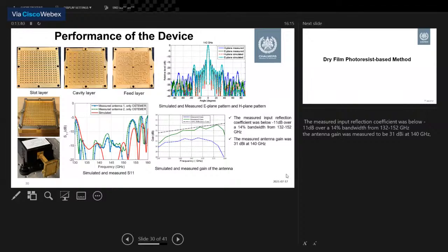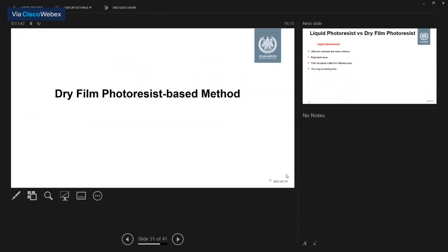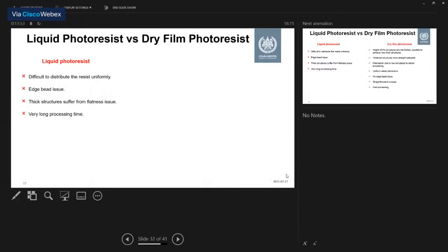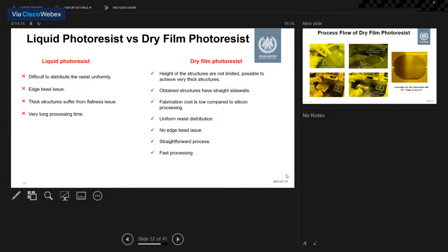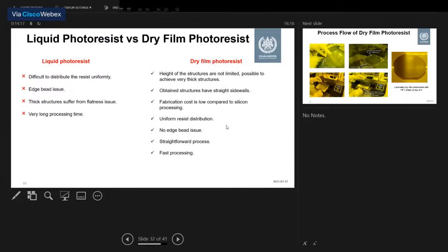But when we use this SU-8, we face some issues or complications. That's why we think about another photoresist, which is dry film photoresist. So the challenge of using liquid photoresist is it's difficult to distribute the resist uniformly. It has an edge bead issue, which actually affects the final exposure dose. Thick structure suffers from flatness issue. It has very long processing time. But if we consider a dry film photoresist, it can overcome all those issues easily.